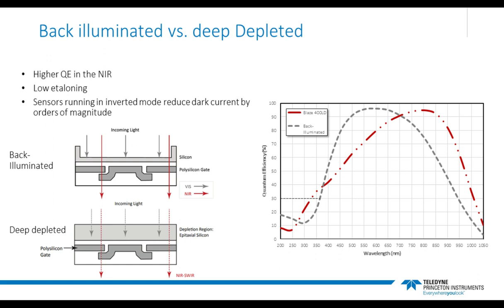However, deep depleted devices typically show much higher dark current than their standard back illuminated counterparts, which can be a problem in applications that might require long exposure times, so minutes or even dozens of minutes. So recently, modern sensors have been introduced that run in inverted mode. That's a mode that can really reduce these restrictions as the dark current is lowered by orders of magnitude. So as such, these deep depleted sensors provide, up to now at least, the state of the art in terms of detection efficiency in the NIR.